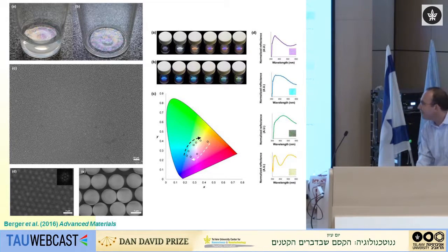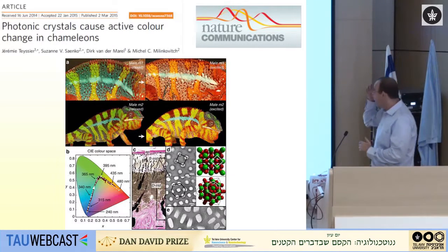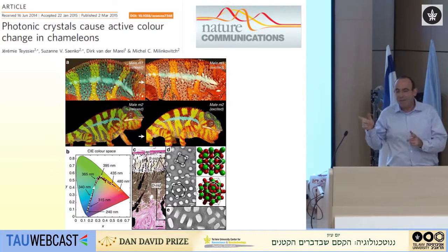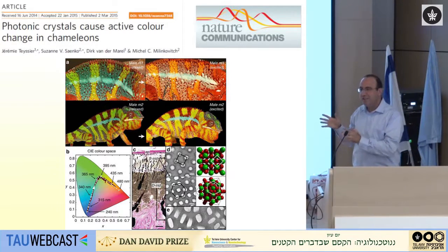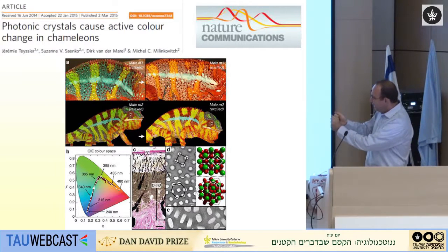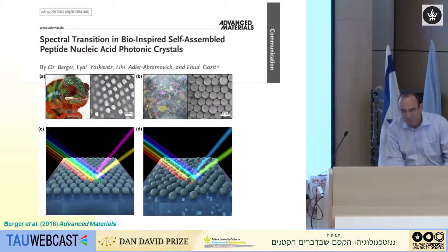During the time that we wanted to publish it, there was a very nice work, not from our group, from a group in France, on the way that chameleons change their color. This is by guanine, our same guanine photonic crystals, and the changing of the spacing is based on the changing of the ionic strength, and thus you can have a rapid change of color by using photonic crystals. So we can do the same thing with our system.